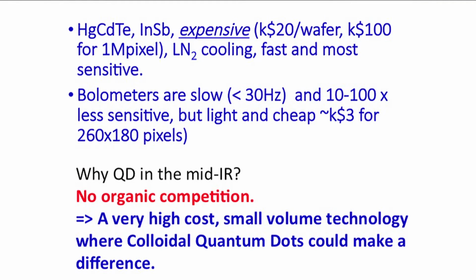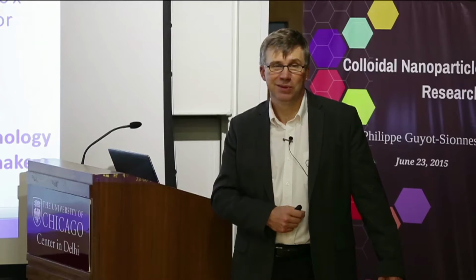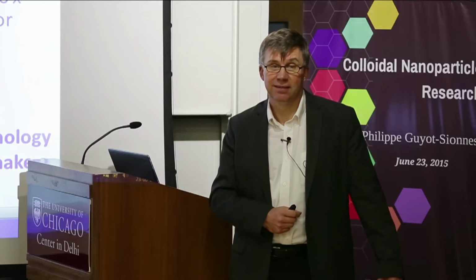So why quantum dots in the mid-infrared? Well, first, quantum dots are good when there's no other competition, and from solution process material. And so there's no organic competition in the infrared, that's for sure. Organics cannot work in the infrared. Does anybody have an idea of what the highest luminescence quantum yield for an organic dye at 1.5 micron, which is not even entering the mid-infrared, is? So 1.5 micron photoluminescence quantum efficiency of a dye, the best number. Oh, it's about 10 to the minus 5.